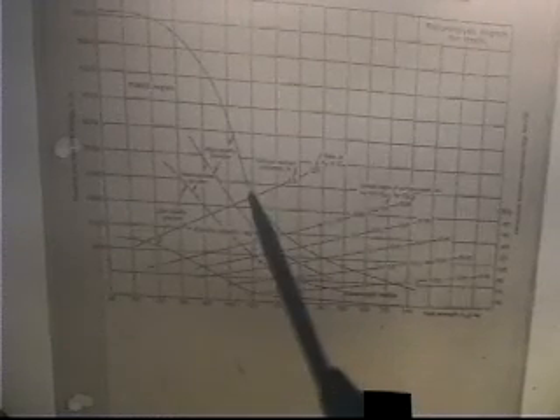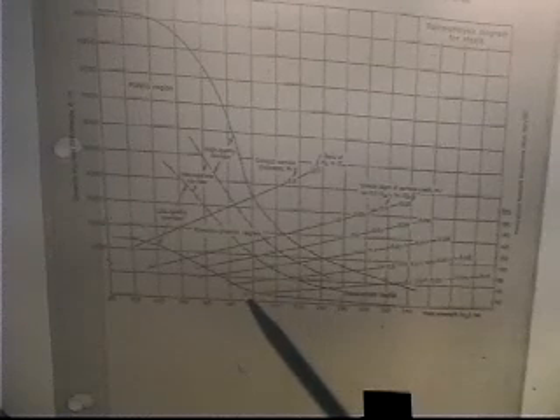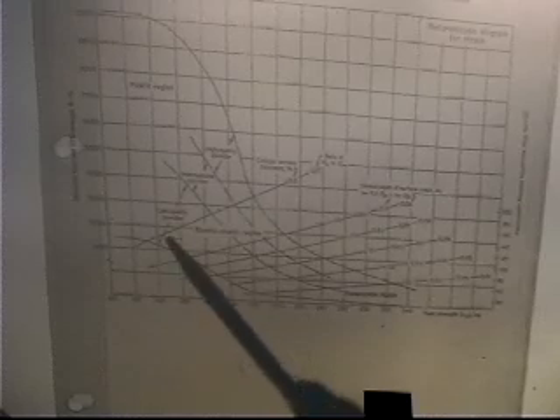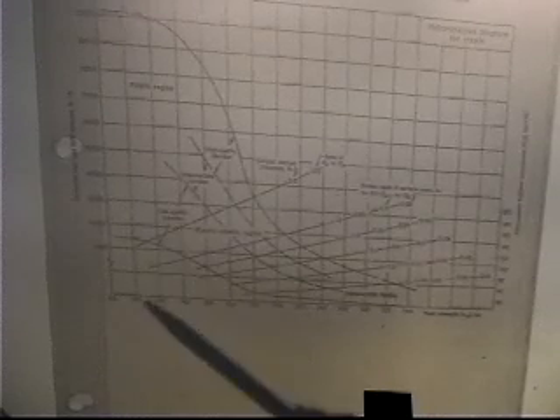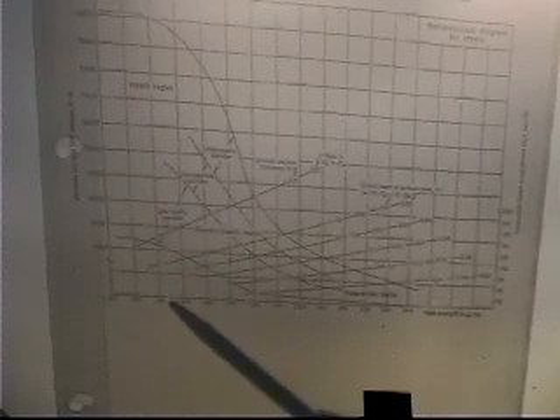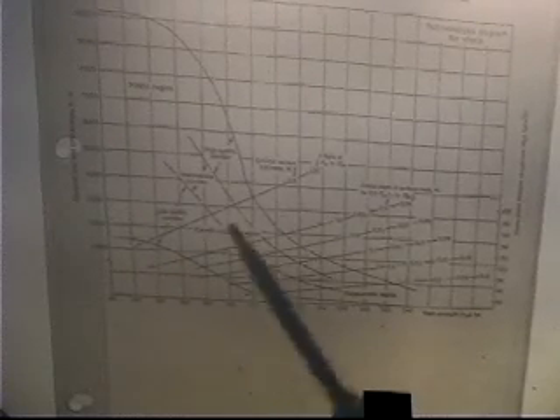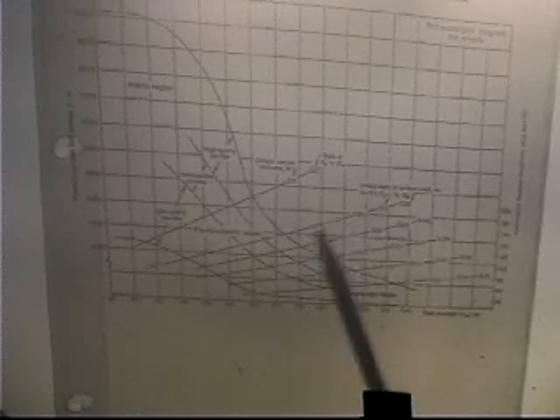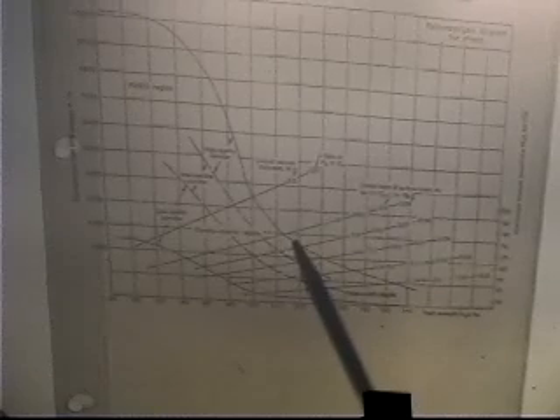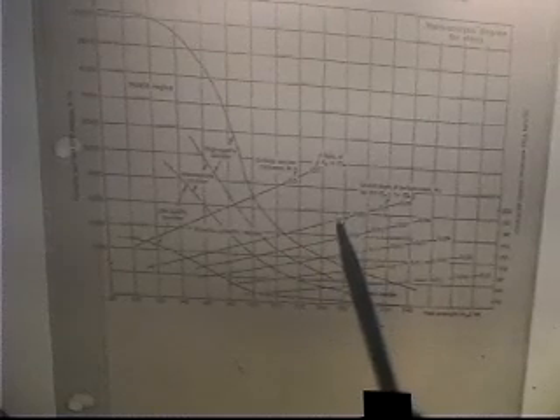So you want to, what type of strength? Well, you don't want to go, according to Pellini, above 180 KSI. The Navy one time had a program for HY 180 steel. Actually, we're down in the 130 range right now. Actually, we're in the HY 100 is what we're building hulls out of right now. But in fact, the Seawolf was an HY 130 submarine when you got to the weld metal, because they had a high side chemistry. I don't know if you want to talk about the Seawolf sometime, but I was one of the 5 people brought in by the chief engineer of the Navy to oversee what General Dynamics was doing, to make sure that they were doing it right after the failure.